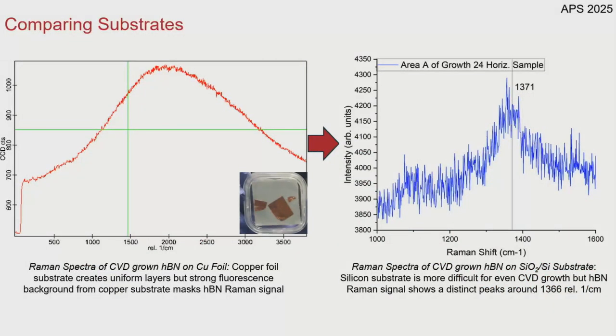Now, the typical method of chemical vapor deposition using catalytic substrates has a problem. If you directly try to characterize this using Raman spectroscopy, copper fluoresces quite a bit. If you put it directly under there, you can't necessarily see if you have hexagonal boron nitride on the surface. You often have to transfer it onto a dielectric substrate that's not going to interact with the Raman so that you can determine the presence of a hexagonal boron nitride peak within the Raman spectra.